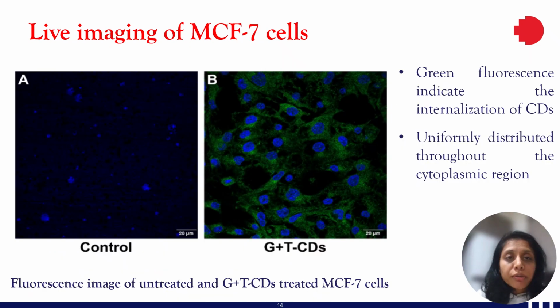This is the comparative fluorescence images of untreated and carbon dot treated MCF7 cells. The imaging results demonstrated a significant contrast between the treated and untreated samples. While the untreated cells showed negligible fluorescence, those incubated with glutamic acid and tryptophan carbon dots displayed strong green fluorescence, indicating their efficient uptake. The strong and stable fluorescence, along with the demonstrated biocompatibility, positions these amino acid derived carbon dots as promising candidates for bioimaging applications.